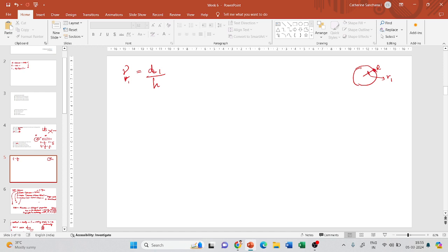It is much lesser than at radius r, so the strain is different, but the height is constant, which means at each radius, my strain rate will vary because my strain is varying. So this is for a parallel plate geometry.